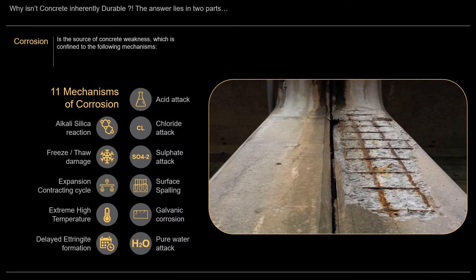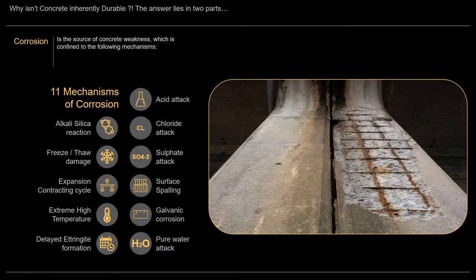Freeze-thaw damage, water gets absorbed into concrete and it subsequently freezes. Obviously, it causes expansion and breaking of the surface. Straightforward expansion from wetting and drying cycles. If concrete is wet, it expands. If it dries, it shrinks. And if it's fully restrained, it can crack. Extremely high temperatures, if we have fires, particularly in tunnels, it's not the fire that actually damages the concrete to a huge extent. It's the moisture content of the concrete, which gets superheated as steam and can cause breaking and delamination of the